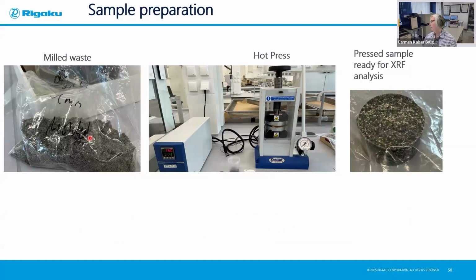So, of course, it still looks very heterogeneous, but we have tried to make it as homogeneous as possible by undergoing the different steps in the preparation. So after we have got a representative sample from what we had, we can try to split this material again and then try to prepare a pressed powder. Or because it has a very high organic content, we can use what we call a hot press. So this is a press machine, but it has an attachment where we have heating plates, and the heating plates help to not only press but melt the material to be able to get this kind of sample that you see here. So it has a very smooth analytical surface with a nice analytical height, because we need infinite thickness for the analysis of not only the light elements but also the heavy elements.